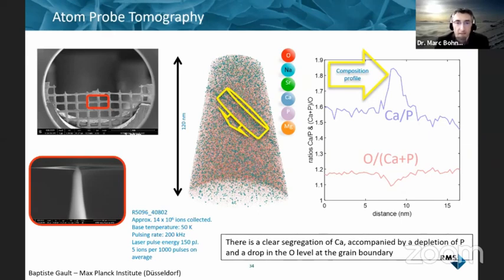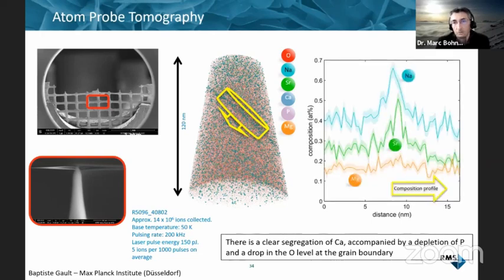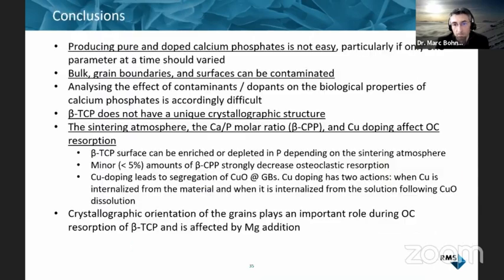And then second, he found a grain boundary that you can see here. You see the size, it's 120 nanometers. And going through this grain boundary, you can see that the calcium to phosphate ratio varies. So the grain boundary does not have the same composition as the grain. And also in this sample that was not fully pure, we saw that there was an enrichment in strontium and sodium at the grain boundary.